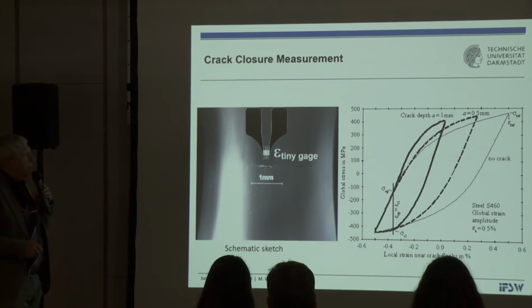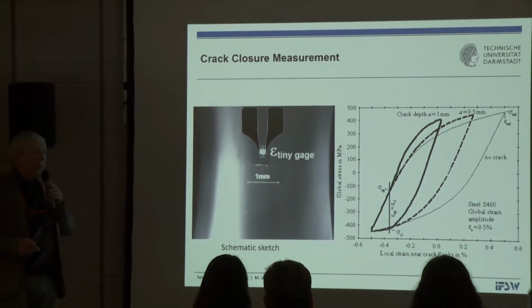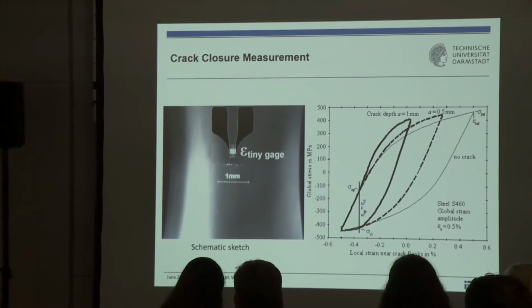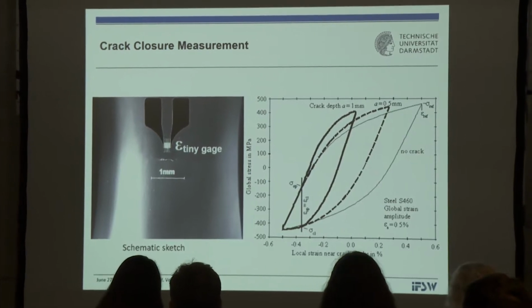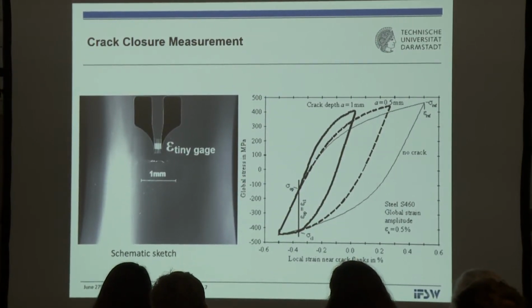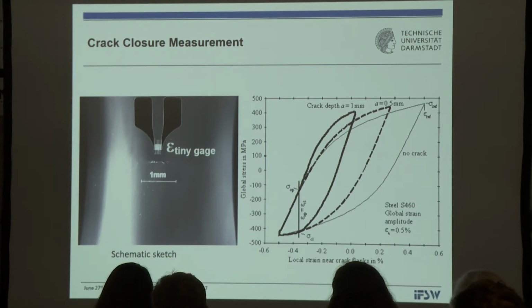I'm very much in favor of accepting that there is crack closure and crack opening. Crack closure and crack opening, as we understand it, is one driver of nonlinearities and of sequence effects, especially in this stage, but also in the long crack stage, which I'm not talking about today. In this schematic sketch, you see an initiated crack of nearly 0.5 millimeter. We mounted a strain gauge as closely as possible behind this crack, and monitored what happens if you apply to this material, under global strain control, some elastic plastic deformation which causes this crack to initiate and to grow.